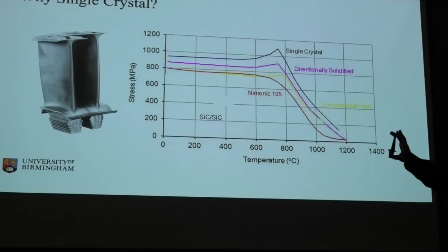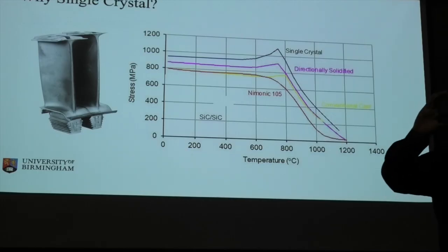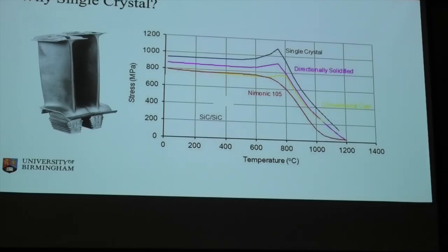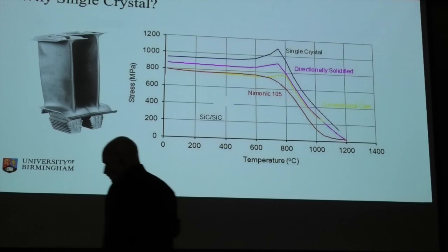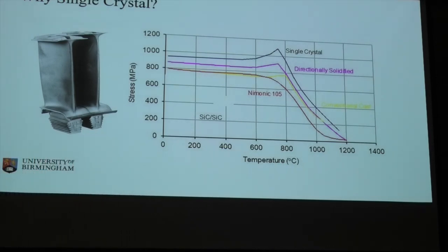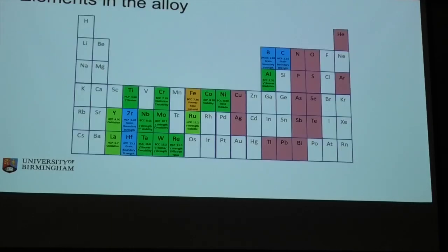The equiax one is the longer one. So the one with lots of different grains in all orientations actually stretched longer over the duration of the test. The single crystal one kept its shape. I can pass it around, it's just a turbine blade. But you can see how that's improved over the generations of material. We've got more of that ski jump, that ramp up, because we've engineered the alloys, and we've got that drop off, which has given them a much stronger material at higher temperatures. But to do this, we've thrown the kitchen sink at it.